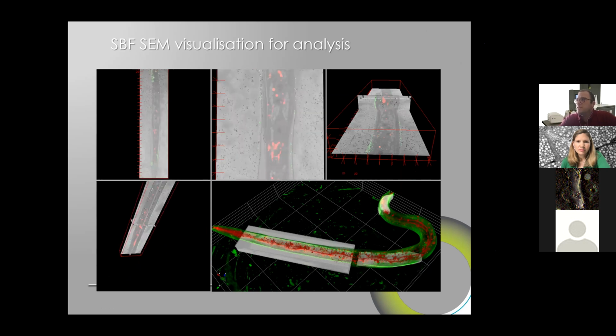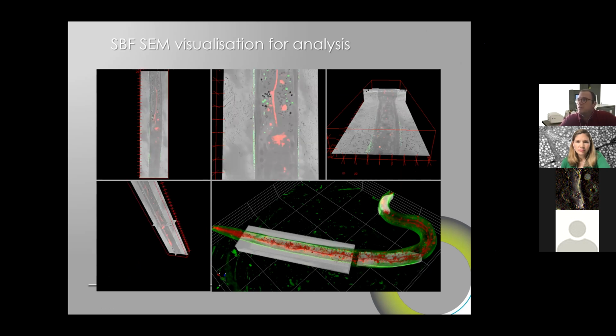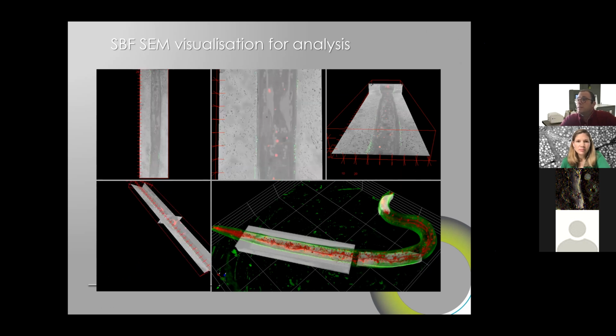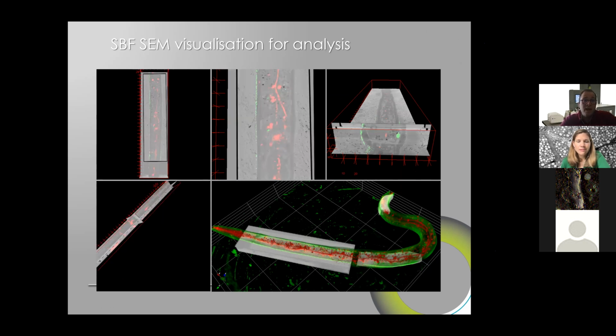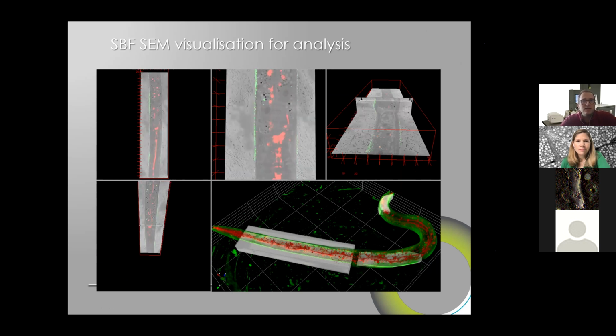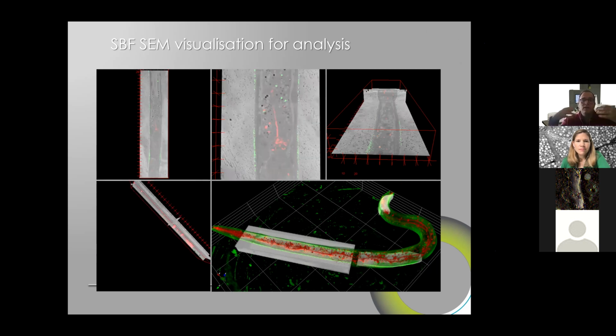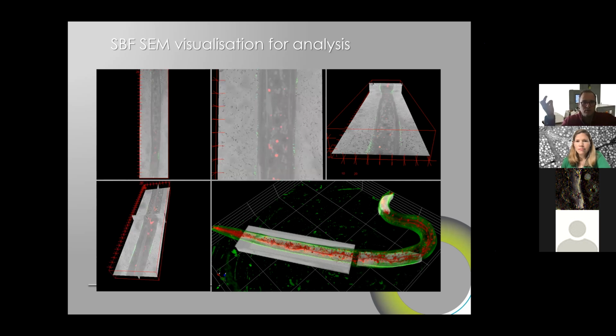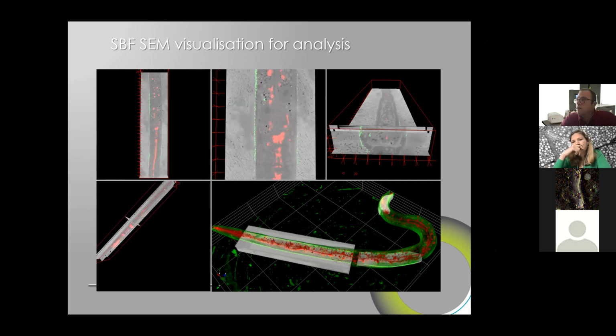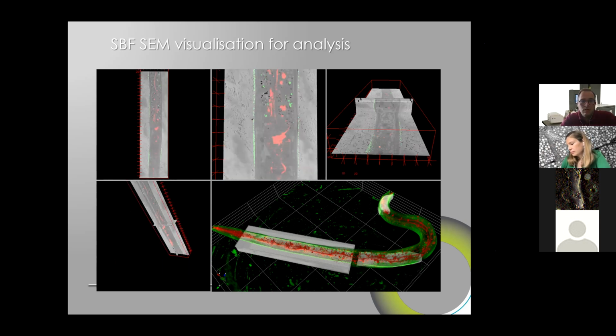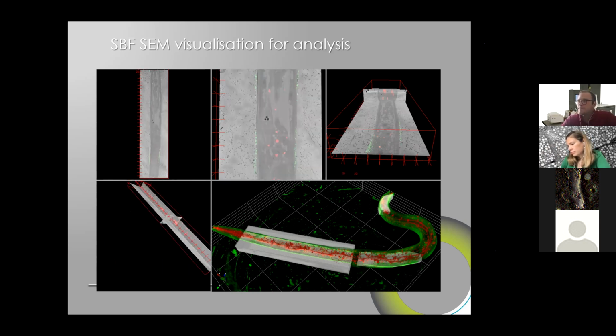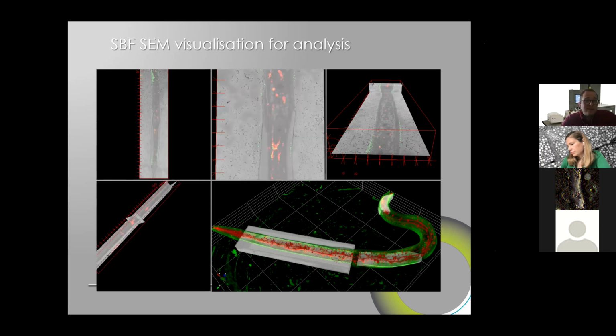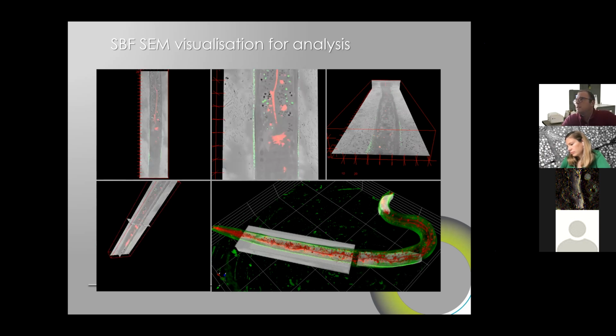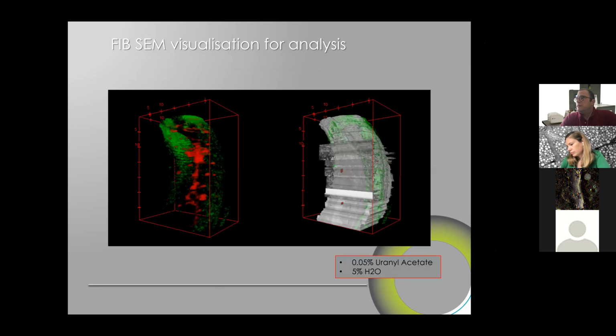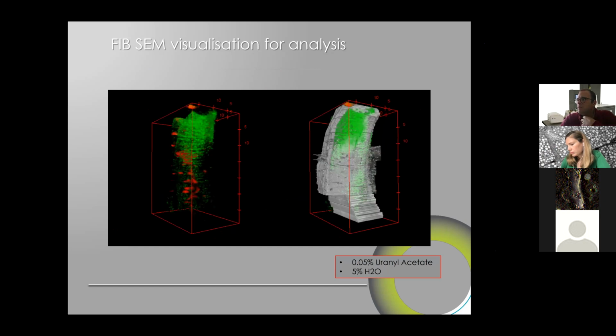So as you can see, the matching is quite good, and this is expected in a way, simply because we're looking at the same volume, both in light microscopy and in electron microscopy. And since we're always looking at the block and not at the sections, we're looking at unaltered structures. So the matching is ideal, if not to say optimal. So this is a side effect, but a quite interesting one. So that's the way we did it. That's the visualization, and all of this combining was done with eC-CLEM.